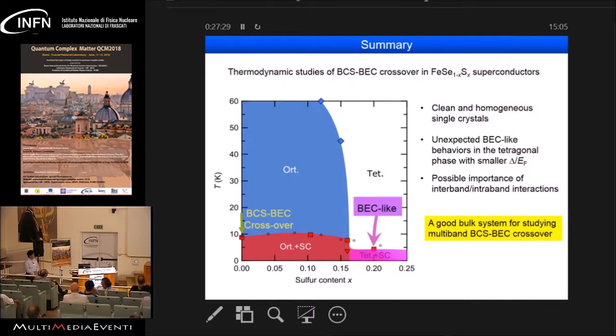Okay, so let me summarize my talk. This is the phase diagram we have obtained. We have a nematic phase transition line coming down like this. Here in the nematic phase, we have observed evidence for BCS-BEC crossover, meaning that we have a large delta over EF, and we have signatures of large superconducting fluctuation. But if you go into the tetragonal side, first of all, the TC gets lower and delta over EF becomes smaller. However, we get evidence for a BEC-like state, which is very unusual, okay?